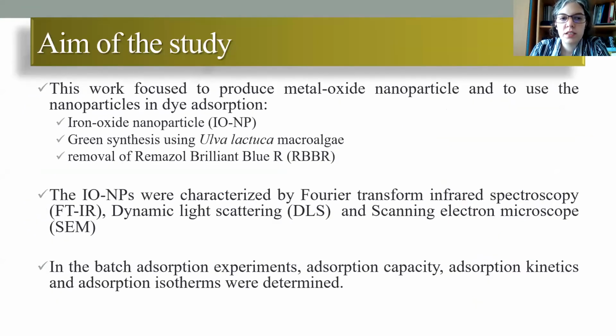In this study, we focused on producing metal oxide nanoparticles to use in dye adsorption. So we produced iron oxide nanoparticles using Ulva lactuca macroalgae via green synthesis to remove Remazol Brilliant Blue R dye. In this study, the nanoparticles were characterized by FTIR, DLS, and SEM. Also, in the batch adsorption experiments, adsorption capacity, adsorption kinetics, and adsorption isotherms were determined.